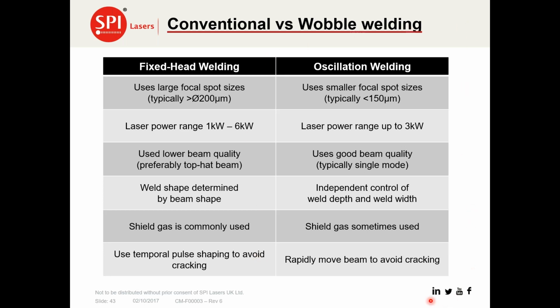Oscillation welding, or wobble welding it is sometimes referred to, uses a much smaller spot size with lower power ranges, and uses very high beam qualities, typically single mode, where we can actually shape the weld by using the oscillation parameters to control the relationship between weld depth and weld width. Quite often we do need some shielding gas, but there are some applications where it is not necessary. And we can rapidly move the beam to avoid cracking in crack-sensitive alloys, and also to control the heat input and the amount of melt that is being generated.